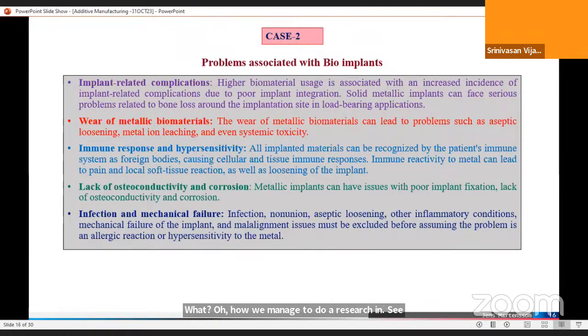See here, the problems with the bio implants are clearly discussed. We can classify these problems associated with bio implants into different categories, based on some journals. Implant related complications: higher biomaterial usage is associated with an increased incidence of implant related complications due to poor implant integration, that is, the material's ability to integrate with the bone. Solid metallic implants can face serious problems related to bone loss around the implantation site in load bearing applications. And metallic biomaterials wear, that is, aseptic loosening, metal ion leaching, and even toxicity. Toxicity means some people may have allergic reactions if they have some implants.